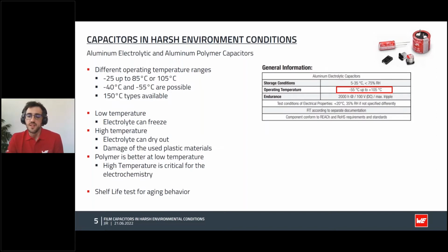In general, aluminum electrolytic capacitors with a wet electrolyte perform quite badly at very low temperature, and it may even freeze. That is why we have parts with different lower temperature ratings, from minus 25 degrees down to minus 55 degrees. These kinds of capacitors actually perform very well at high temperatures with lower losses. But the problem is that the electrolyte will dry faster from the heat and dry air, so the expected lifetime will be very short.